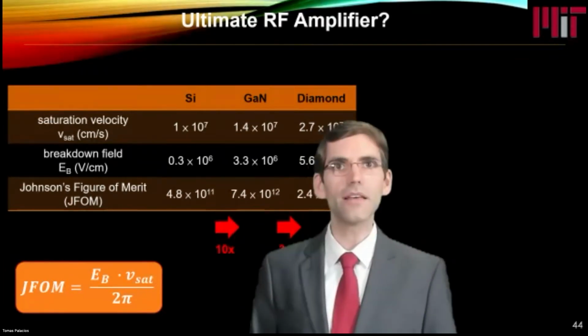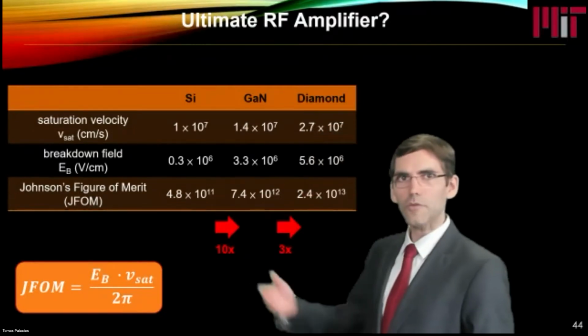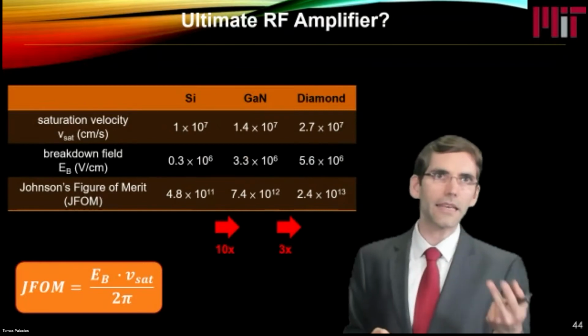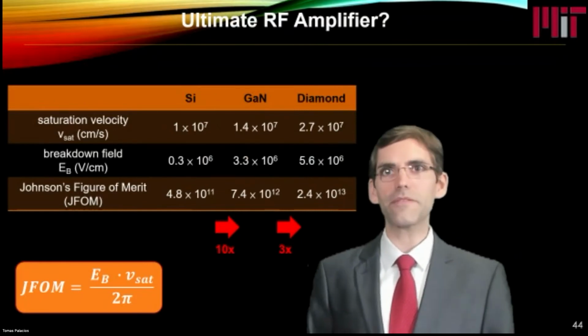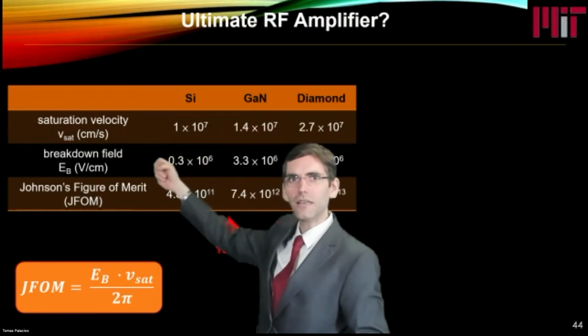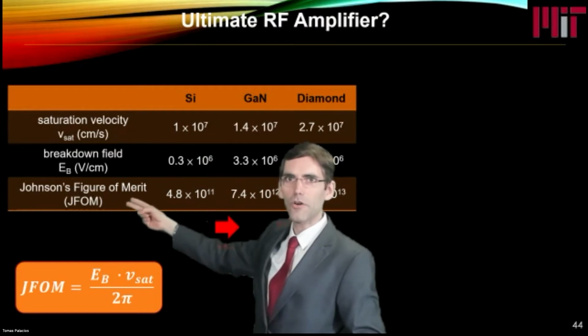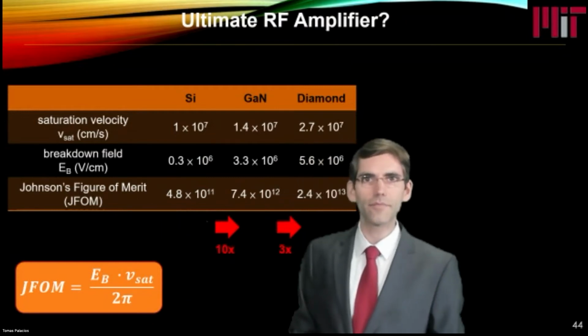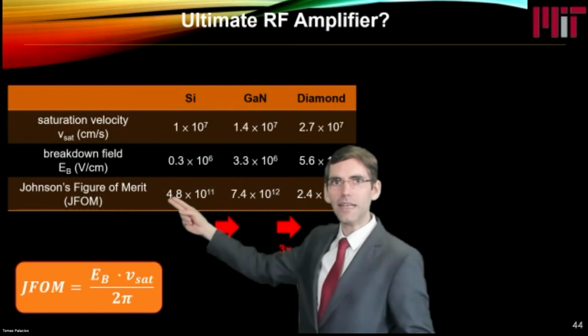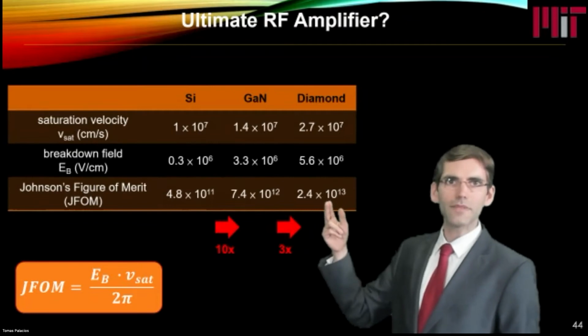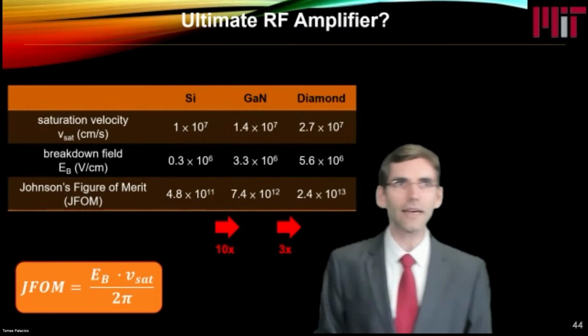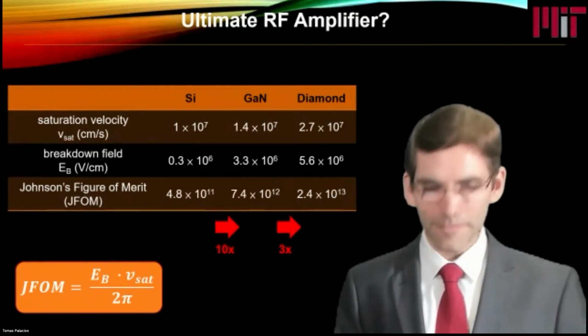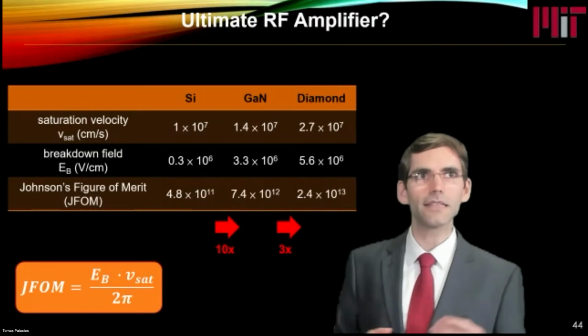But then the question is, sure, we can integrate transistors, but what is the very best we can do? What is the ultimate limit for transistor technology in terms of RF amplifiers? So for that, we've looked at different semiconductor materials and the key figures of merit, the key parameters for RF amplifiers. In this case, saturation velocity, breakdown field, and we combine both parameters in what is called the Johnson figure of merit. And of course, gallium nitride is much better than silicon, roughly 10 times better. And diamond is potentially also better than gallium nitride by a factor of 2 or 3. Can we do better than this? Yes.